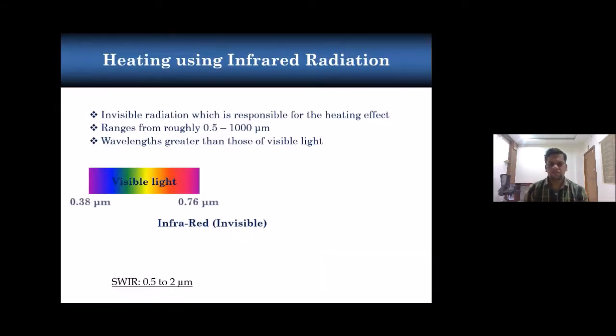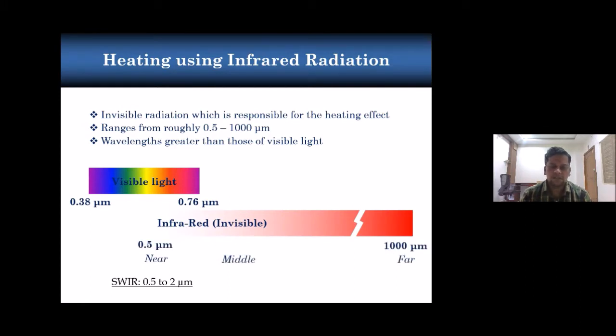Now coming to infrared radiation. If you see the total electromagnetic spectrum, infrared radiation will fall between 0.5 microns to 1000 microns. Over this range, we can see only the invisible part from 0.5 to almost 100 micrometers. This is further subdivided into three regions: short wave infrared, medium wave infrared, and far infrared. Out of these three, short wave infrared is used for simulating the aerodynamic heating, like for heating any object. Short wave infrared ranges from 0.5 microns to 2 microns. From 2 to 100 microns, it is medium wave. This medium wave infrared heating is used for car paint drying and the paper drying industry.